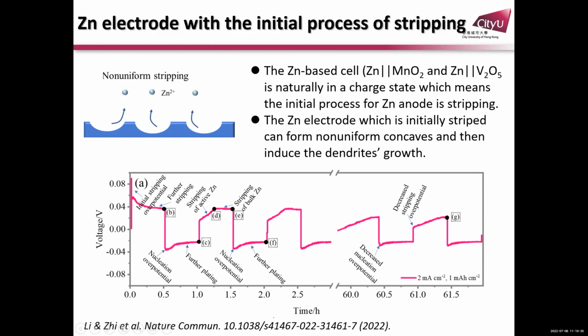That starts from the initial stripping, with the overpotential, then the nucleation overpotential, then stripping, then plating, and then we start plating. Then you will see the second stripping process start from stripping of active zinc to bulk zinc. Then another plating, with a similar shape, starts from two stages of stripping: stripping of active zinc, stripping of bulk zinc.